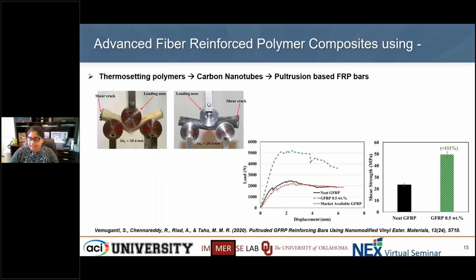Comparing the shear strength itself, this is interlaminar shear, so we can comment on the bond that was created due to the addition of carbon nanotubes. We saw a very good improvement of up to 110% increase in shear strength when you look at just plain pultruded bars without any carbon nanotubes, compared to pultruded bars with carbon nanotubes. So these are the two improvements we saw.